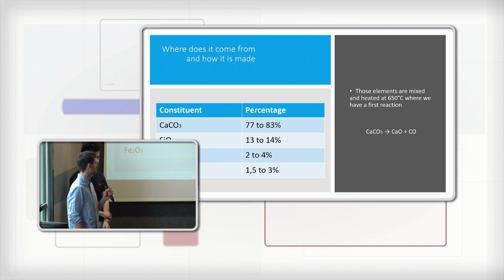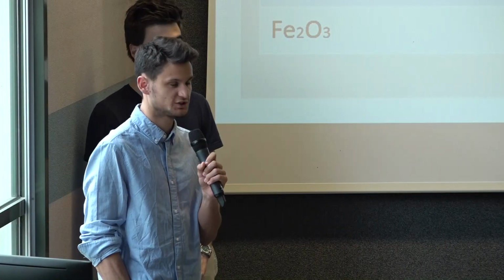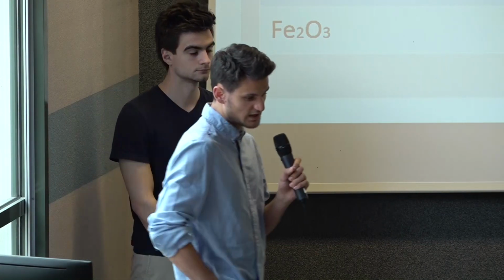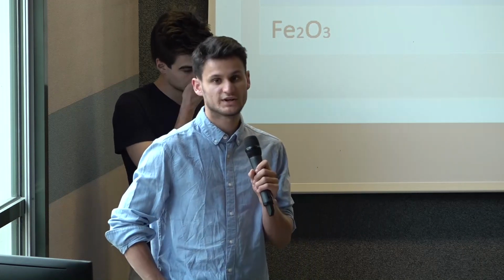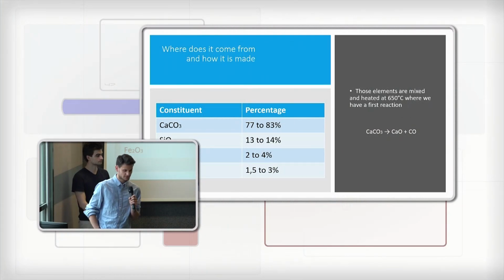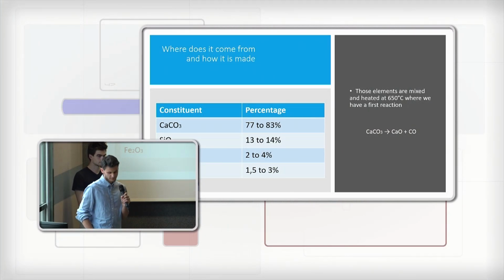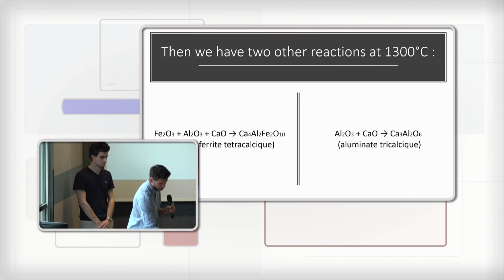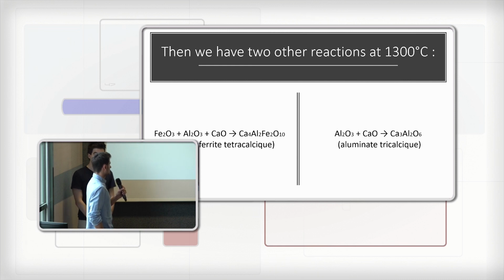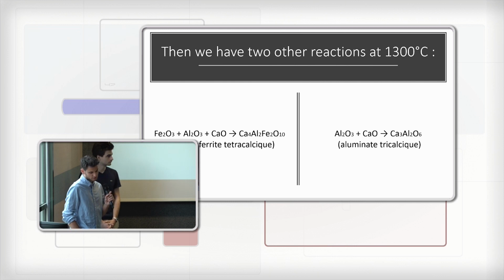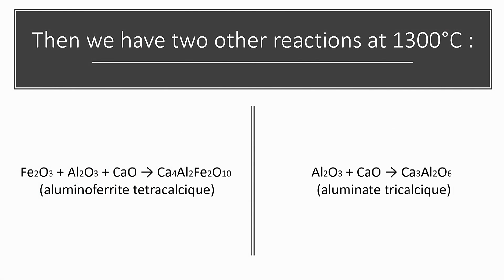So we take our powder and we put it in an oven at the first temperature, which is 650 degrees. At this temperature, we have this reaction. At this temperature, the calcium carbonate is decarbonated. And after we increase the temperature to 1,300 degrees, where we have two reactions. After that, these two reactions are followed by other reactions, which will give the clinker. Then we add gypsum to slow down the cement hardening. And at the end, we have the cement.